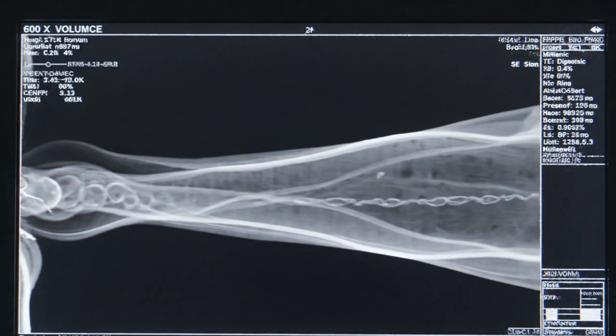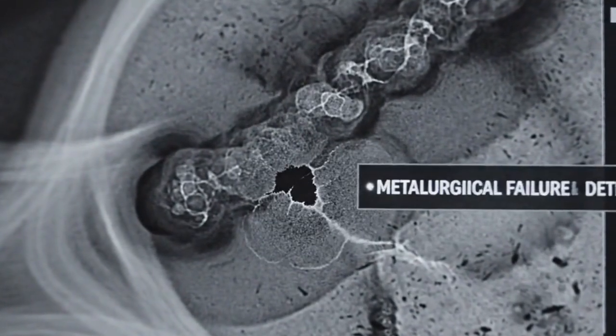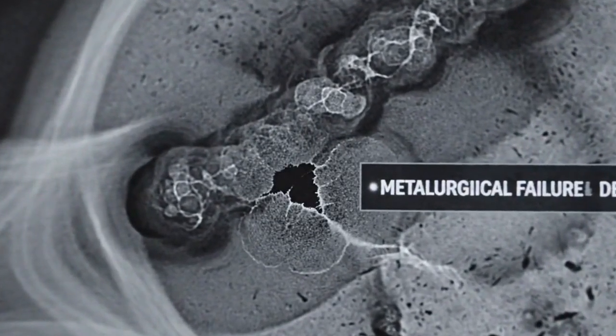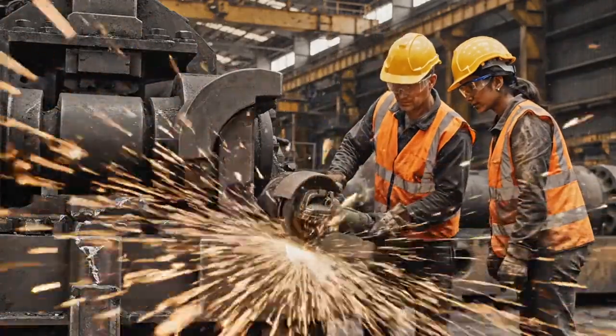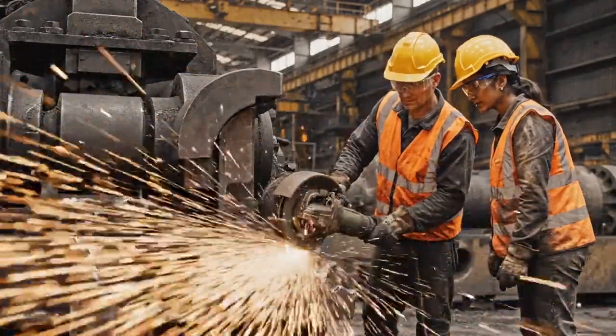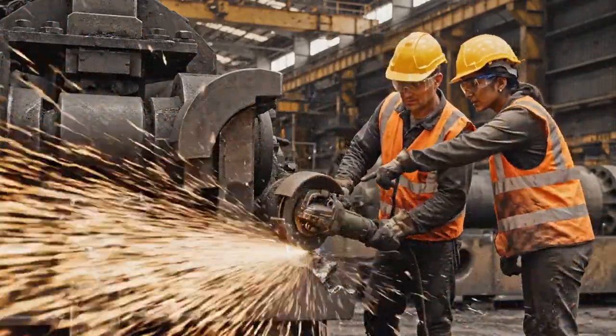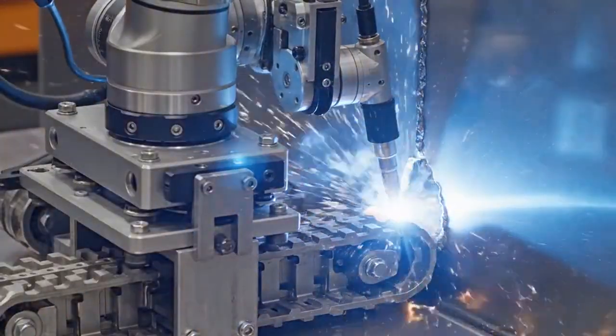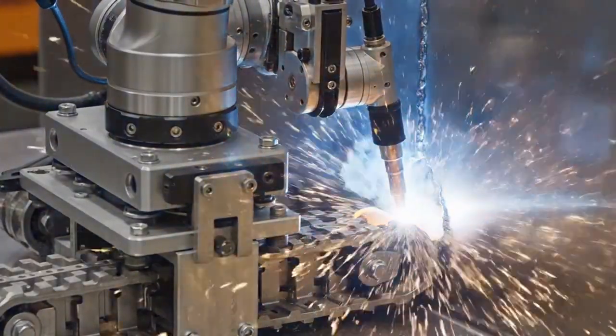These extreme quality control scanners actively hunt for microscopic voids, trapped gas bubbles, or sub-millimeter structural cracks that could compromise the pressure boundary. If the X-ray diagnostics reveal a flaw the size of a grain of sand deep within a welded joint, the robotic welding sequence must be instantly halted, the flawed section mechanically gouged out, and the entire high-precision welding process repeated from scratch.